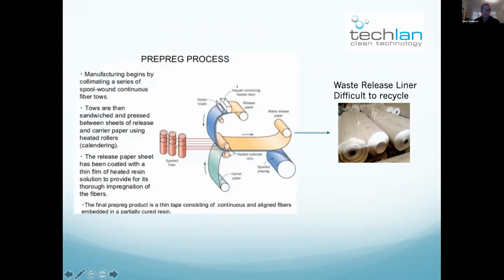Yeah, the pre-pregging process, which you're probably very familiar with. The release liner is coated with an epoxy adhesive. This is then passed through a series of nip rollers. The fiber strands, which are drawn in, are pressed or impregnated into the adhesive. And at the end of the process, the release liner is removed, and this is waste material. And this often goes to landfill.